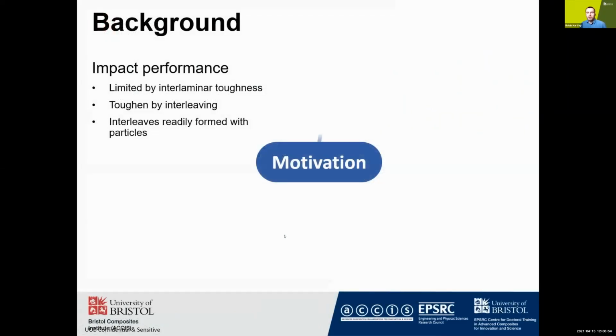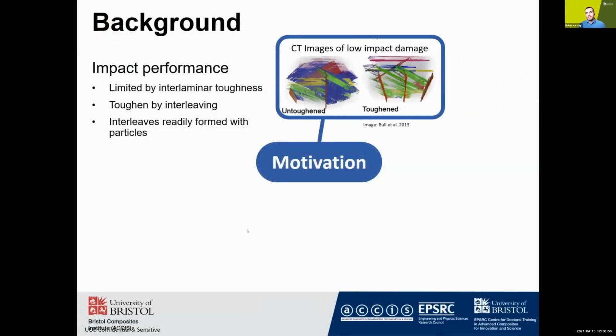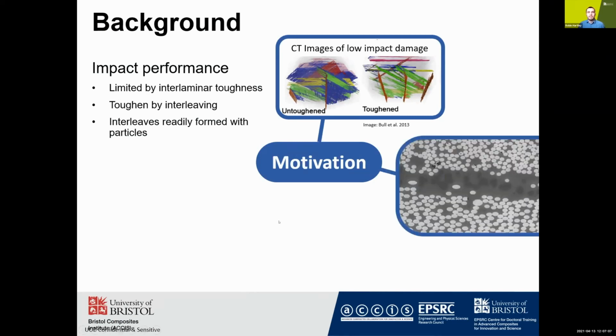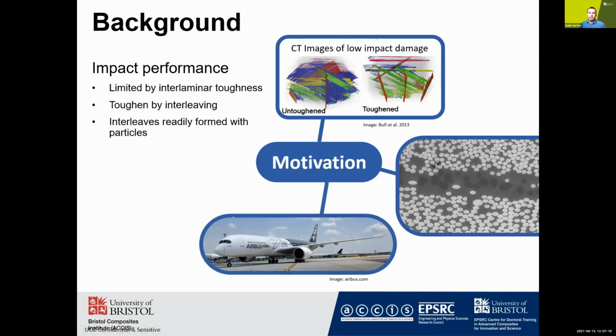So, as we all know, composites are limited by their susceptibility to impact damage, taking the form of cracks that coalesce in interlaminar regions and act as initiation points for catastrophic delamination. An established way of preventing this is to incorporate a tougher region of increased thickness between fiber layers called an interleaf. Interleaf technologies that have been qualified for use on aircraft often use particles to form these regions, as they allow the interleaf thickness to be controlled relatively easily.